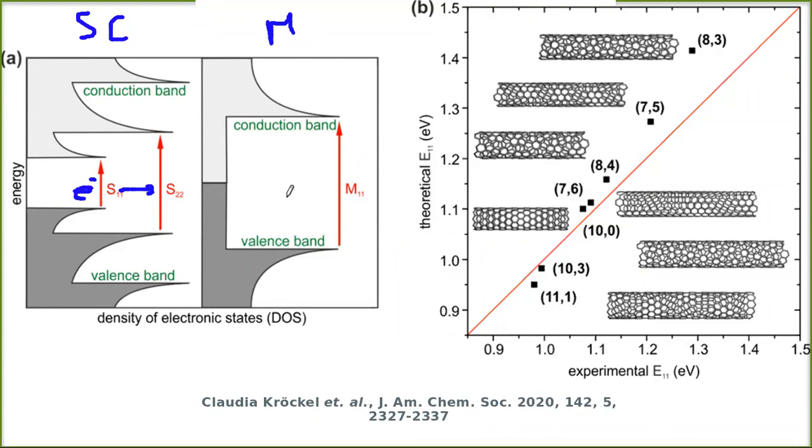And in the case of the metallic ones, that also occurs, but in this case, we need to cross larger or different regions of Van Hove singularities. But what we can tell also at this point is that our semiconducting materials are extracting a lot of these electrons, and the metallic ones, as they are already metallic, don't require a lot of these electrons. They just require a portion of them.